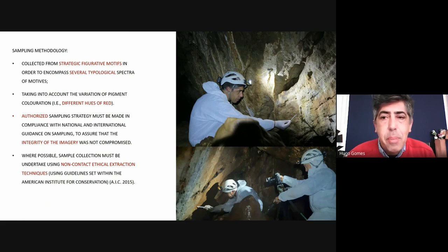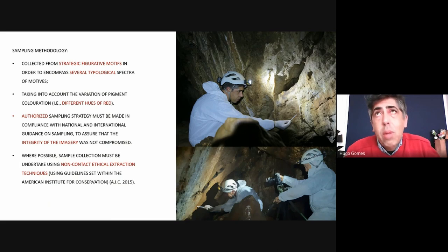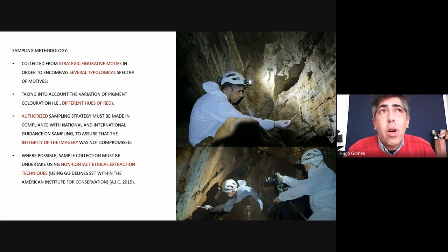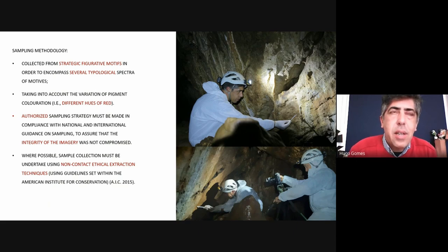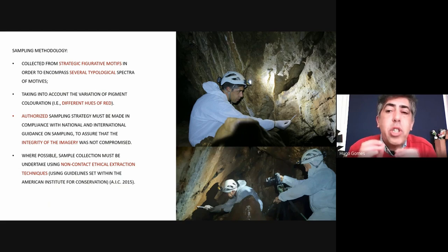The sampling method is as accurate as possible. We use gloves and try never to touch the panels with our hands, clothes, or plastics, because everything we add to the wall paintings becomes at least a trace of contamination. Now, with the Max Planck collaboration — especially dealing with Neanderthal research — if we touch the wall our DNA starts to adhere to it. We use sterilized Eppendorf tubes, tungsten scalpels to keep good samples, and sometimes portable microscopy to verify what we are sampling.